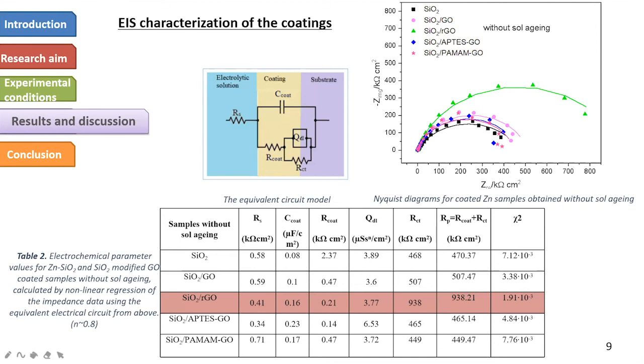Electrochemical impedance measurements. Impedance data were modeled using the electrical circuit presented in this picture. Table 2 contains the corresponding parameters obtained from fitting the equivalent electrical circuit model to the experimental diagrams. This model consists of a resistor as a solution resistance, a resistor and a capacitor in parallel, which represents the electrolyte resistance through the coating and its related capacitance, and a parallel combination here of the charge transfer resistance and the constant phase element of double layer capacitance.